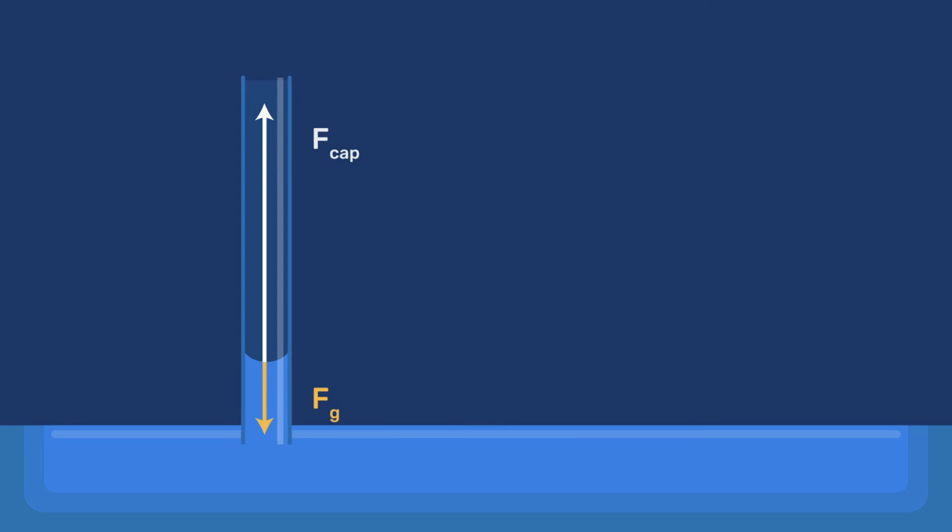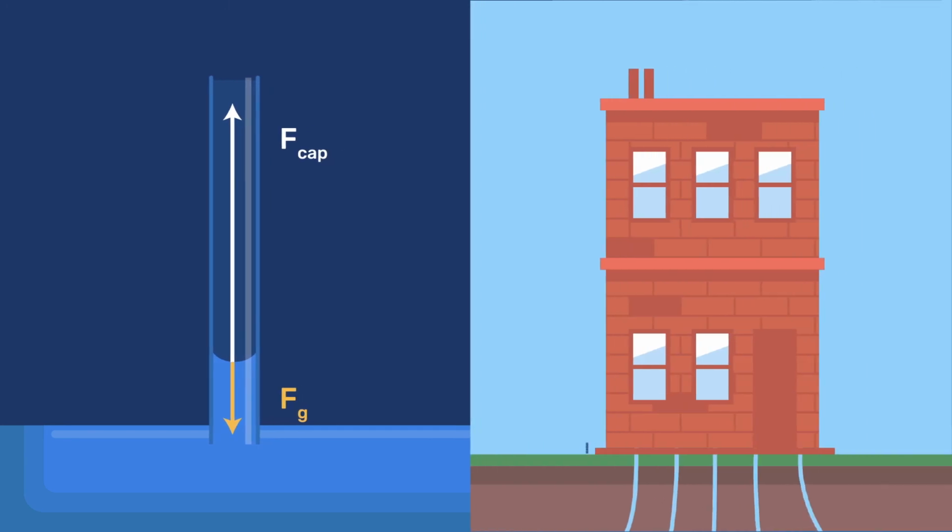These conclusions hold as long as the hydrostatic pressure exerted by gravity is substantially lower than the capillary pressure, which holds up to several meters for most porous construction materials of interest. Where gravity can be ignored, the equations presented hold for the rate at which liquid is sucked into the materials in all directions, including downwards.